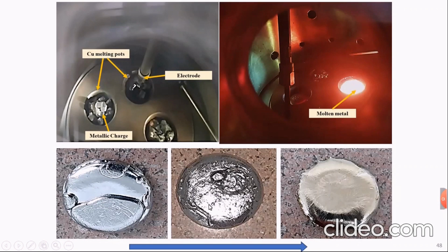Why do we melt again? Because repeating the melting process homogenizes your sample. How many times should I repeat? Some people say 3, some 4, some 5, some 6. No, it's not important how many times. The more important thing is to obtain homogenized samples, because the alloys and elements differ in their viscosity, in their fluidity. So it's up to your sample actually, up to your design system.